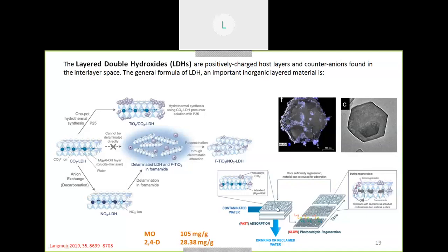They use this material for adsorption of methyl orange and 2,4-D, which is a pesticide. And after a time, they apply the UV light. You can see here, which is a slow process. But when the light falls over TiO2, hydroxyl radicals are produced, and these hydroxyl radicals can again photodegrade the pollutants, which are intercalated between or on the surface of the materials. So this is freeing one more site again. Now the site is again activated and it can adsorb another molecule. So this type of application has been exploited with the combination of adsorption and photocatalysis together.